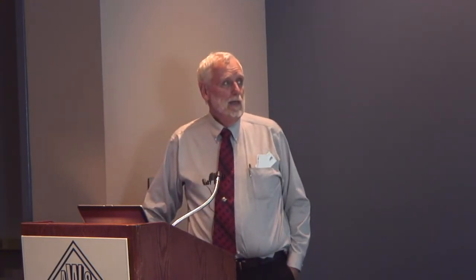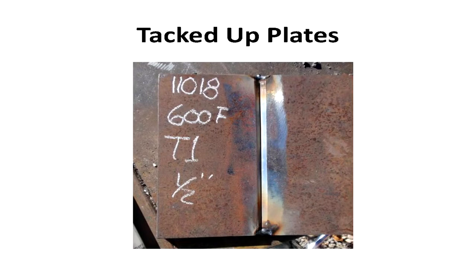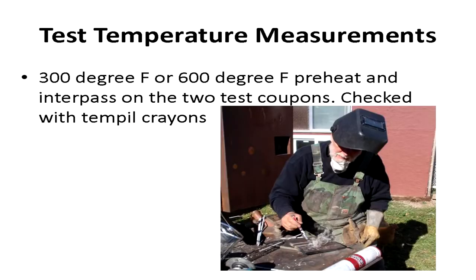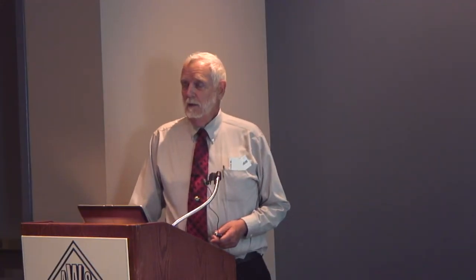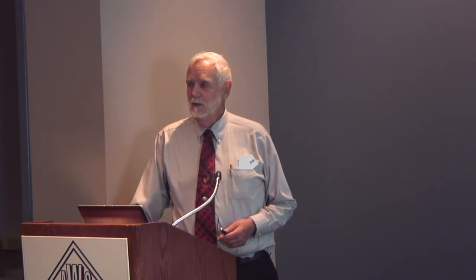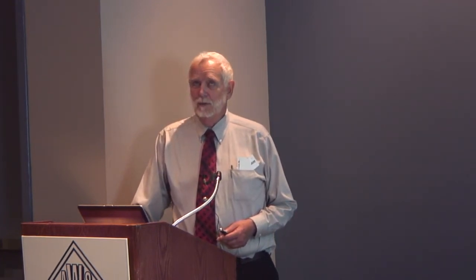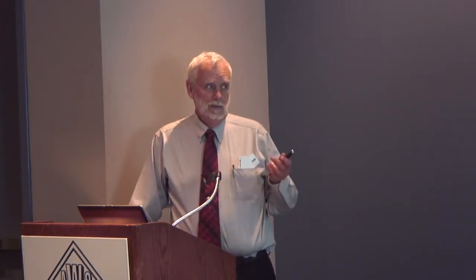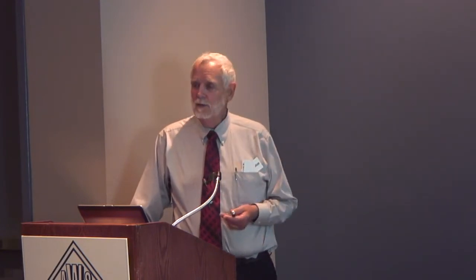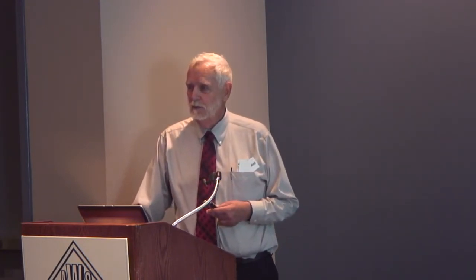So the other one I flame cut the joint. Here I tacked it up. Oh, look, there's my temp stick. Where'd I put it? Oh, always right here. There's my temp stick, and see it smoking? I got the right temperature. And I preheated, the good one I welded at 300 F, and the bad practice, 600 F. And once I got going, it was hard. I had to wait 20 minutes to cool that other one down. It would take 20 minutes to cool down. I kept wanting to squirt it with water, and I just didn't think I should do that.